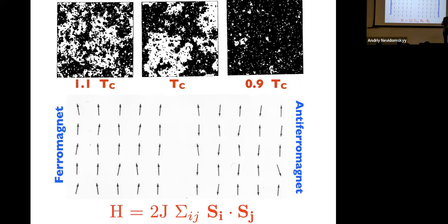And actually, what we're interested in, and we're not the only people, there's other people in this room who are also interested in this, is looking to maintain this sort of disordered state down to the lowest temperatures. There's a couple of reasons we want to do this, but probably the most compelling reason is that if you preclude the conventional phenomenon from occurring, it opens a window for unconventional phenomena to occur. And so if we can maintain this disordered state not by thermal fluctuations, but by, say, quantum fluctuations or by geometrical frustration, then we can end up with an interesting quantum disordered ground state. So that's what we're ultimately looking for.